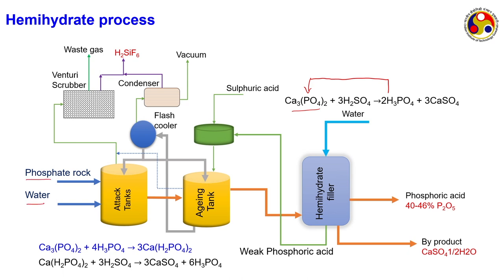You can see there is a phosphate rock and water entering the attack tanks. The attack tanks are where the sulphuric acid is present and this reaction takes place. Then it is sent to the aging tank, where you let the solution stay for nucleation to occur. Once nucleation occurs you have a mixture of solid and liquid, which is then separated in the hemihydrate filter. The hemihydrate filter works in the same manner as for the dihydrate — using a circular pan filter with vacuum applied to separate out the acid.